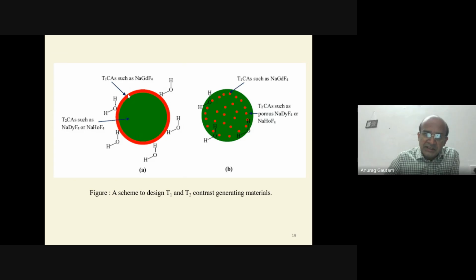If it is both T1 based MR imaging and T2 based MR imaging, that will be a more concrete answer. So here, this is the T1 based contrast, sodium gadolinium fluoride. Iron oxide nanoparticles of smaller size also work as a T1 contrast agent. Very small, 5 nanometer, they work as a T1 based contrast agent. The bigger ones, 20 or 15 nanometer, work as a T2 contrast agent. Gadolinium is always a T1 contrast agent, because its T2 shortening effect is very, very small. It doesn't decrease much time of the water molecule or hydrogen proton.